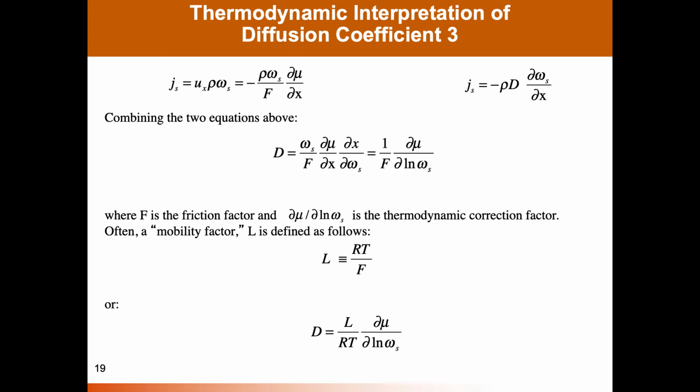and they have a contribution from thermodynamics, because the transport we recognize is driven more fundamentally by chemical potential gradients, but we often write the transport mass flux as being driven by concentration gradients. Now, in a lot of cases, this difference doesn't matter. The concentration gradient and the chemical potential gradient are aligned with one another, and they often change regularly with one another. And so in a lot of cases, this factor will be small, or it will be a constant value, and you never see it in the experimental data, or it's not sorted out.